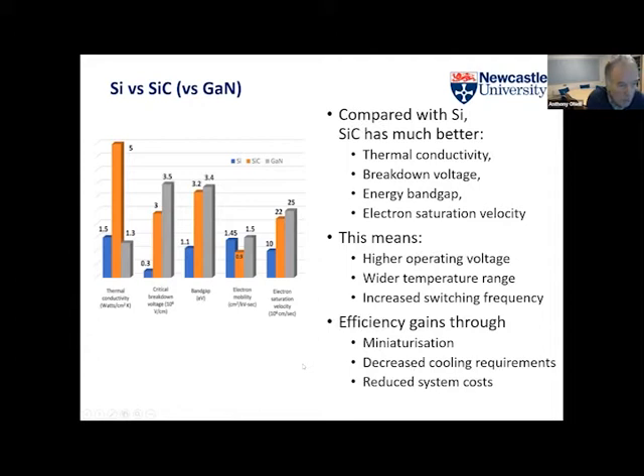That's done largely by silicon at the moment, and the pitch that Michael gave was one which I would of course endorse in this presentation, which is wide bandgap semiconductors have got some great properties. I'm focusing mine on silicon carbide, but I've got gallium nitride in my slide just here. If you just look at the basic properties here, the blue is silicon, the orangey color is silicon carbide, and the gray one is gallium nitride, so I'm less interested in that. You'll notice that silicon carbide's got brilliant thermal conductivity, much better breakdown electric field compared with silicon. Energy band gap, again, a lot bigger, so that's why it's the wide band gap.